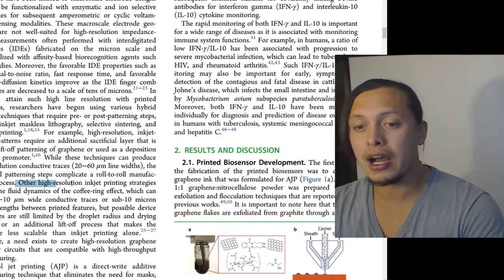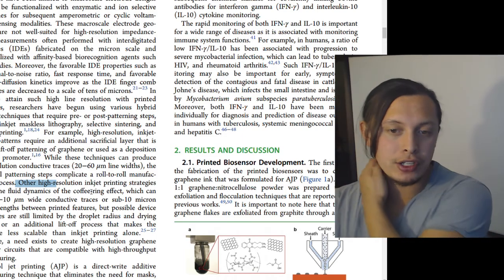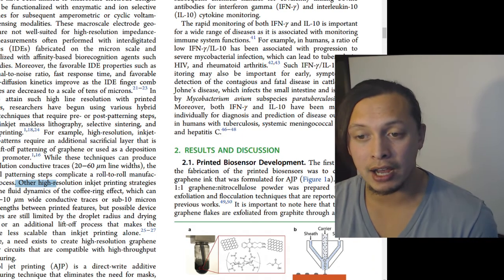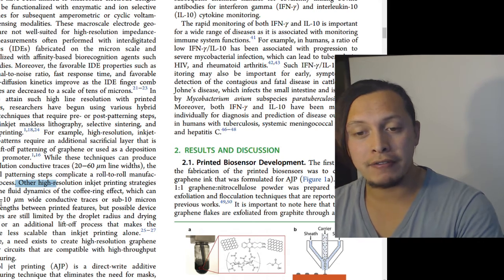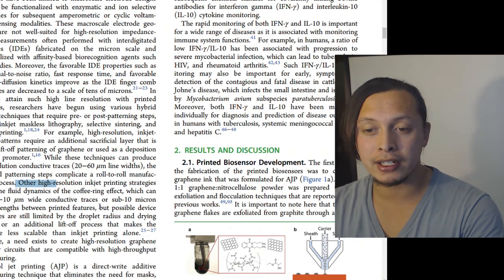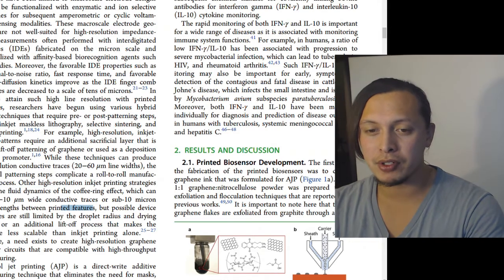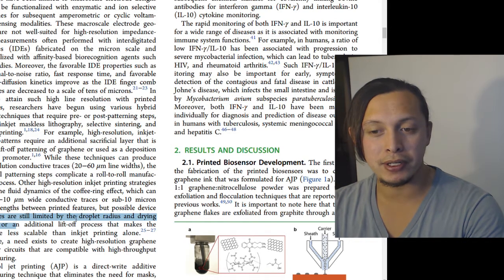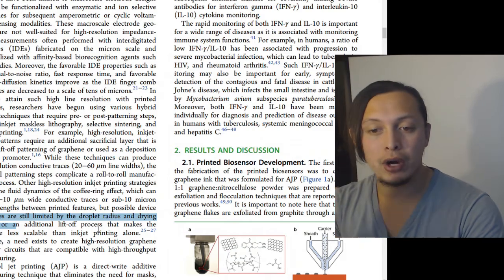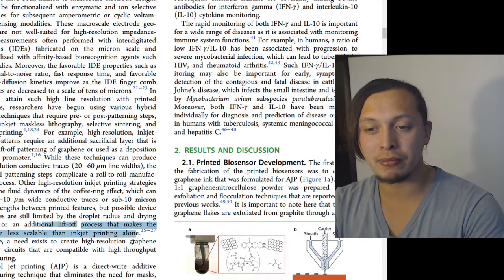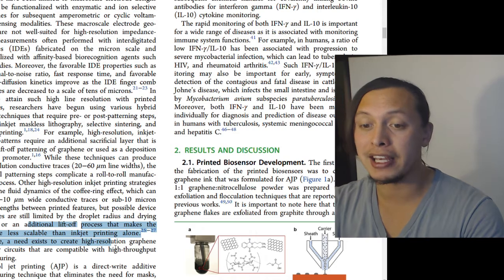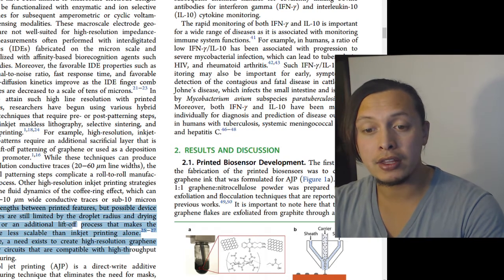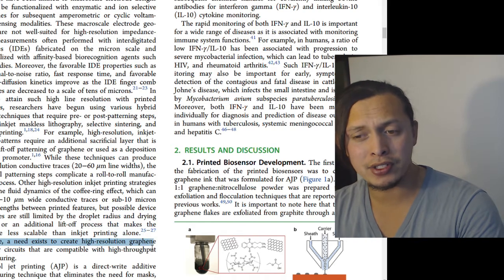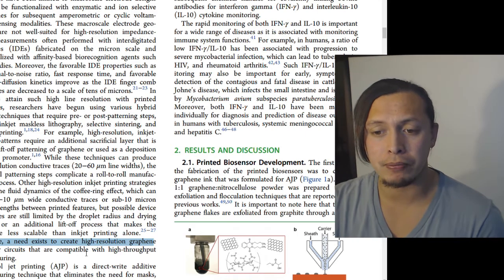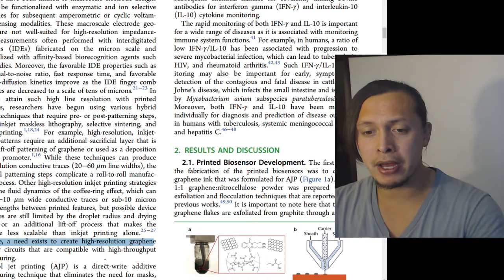Other high-resolution inkjet printing strategies rely on the fluid dynamics of the coffee ring effect, which can create 5 to 10 micrometer wide conductive traces or sub 10 micron channel lengths between printed features. But possible device geometries are still limited by the droplet radius and drying patterns, or an additional lift-off process that makes the technique less scalable than the inkjet printing alone. Therefore, a need exists to create high-resolution graphene biosensor circuits that are compatible with high-throughput manufacturing.